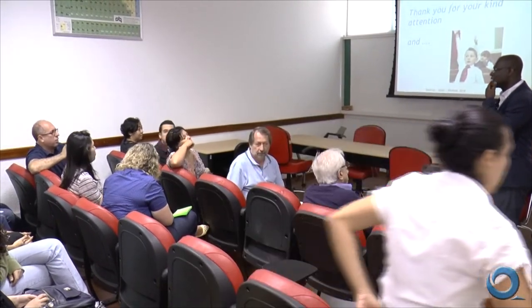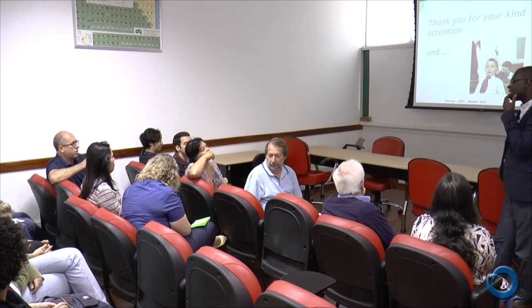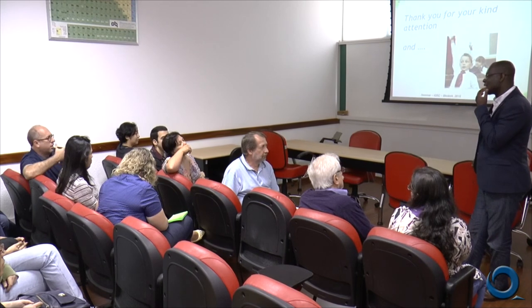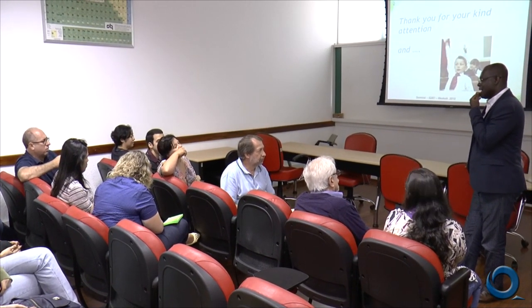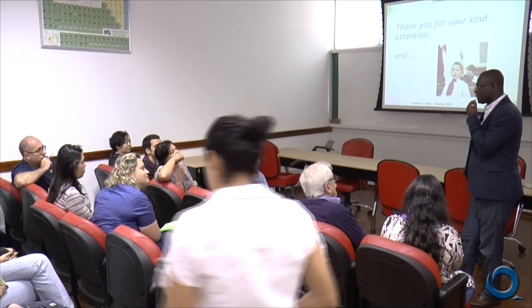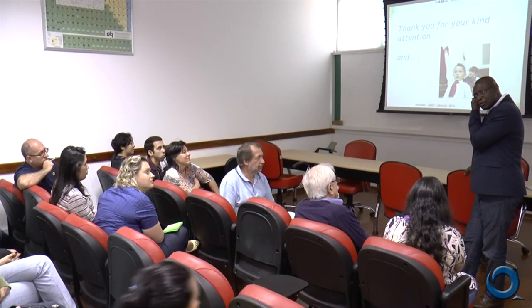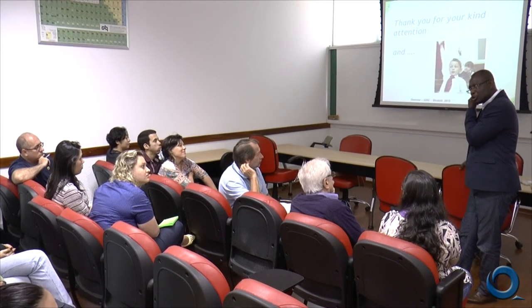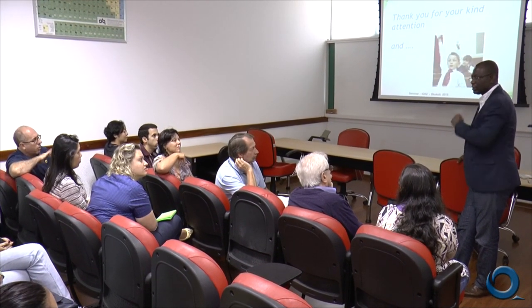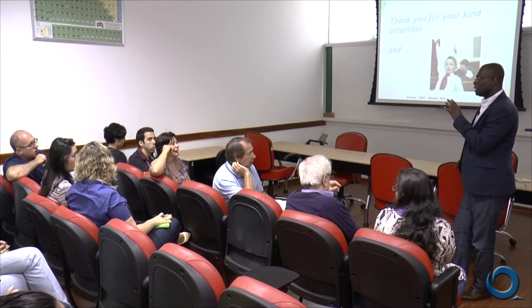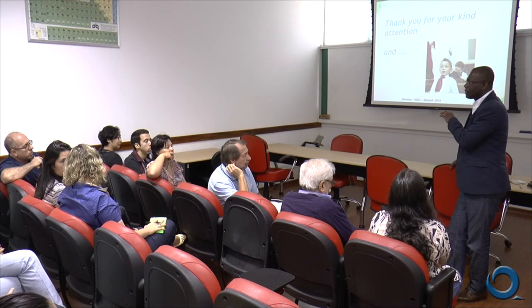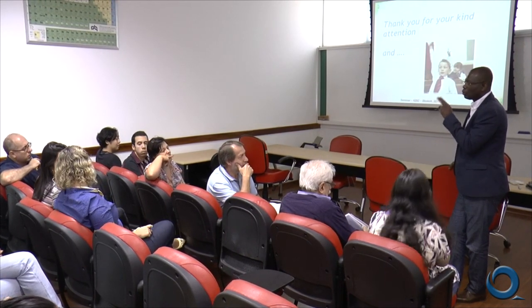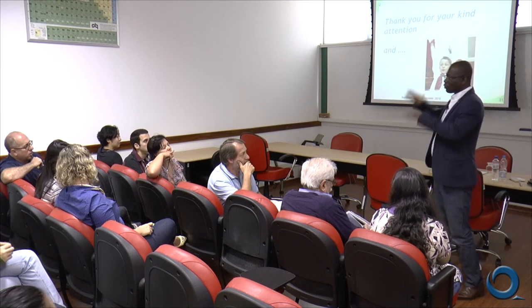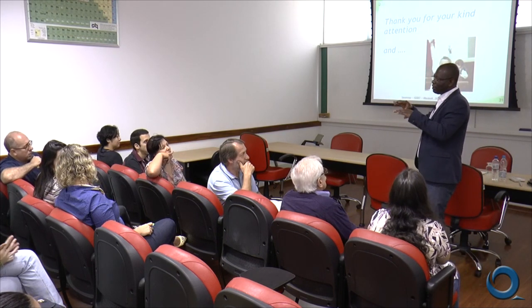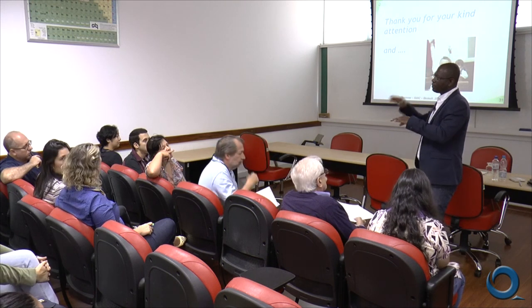Besides the morphology of the particle, like platinum morphology, for example, do you have some characterization that indicates a homogeneous distribution of the palladium or nickel, or some segregation? No, it's not. In this preparation, we changed the polyol method to have the cation. This is not this system. This is to have the modification of the system with the co-catalyst. The problem you have if you work with nickel, for example, is that you have no contrast to see very well the difference between palladium and nickel.